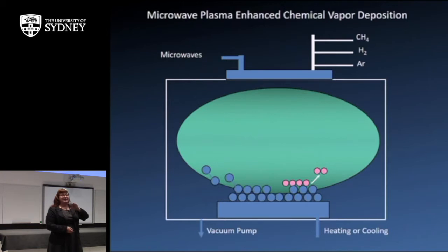Super slow, insanely expensive. I actually have some lab-grown diamonds. They're very beautiful, but that's not what we're trying to do. So we're actually making very tiny little crystals of diamond, nanometers, in a thin film that have a bunch of grain boundaries. And we're doing it by chemical vapor deposition. So it's just methane and hydrogen. It's a microwave plasma generator. And it makes these interesting species, which end up being C2, which is unusual for diamond growth, to make these types of films. And I think I have a picture.